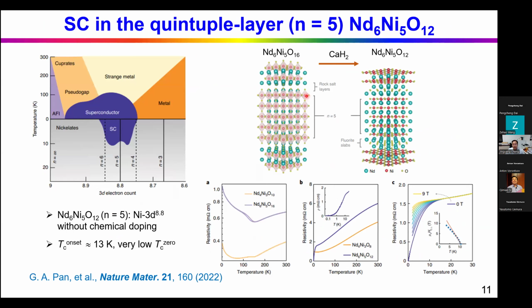Later on, superconductivity was also realized in the quintuple-layer neodymium 6 nickel 5 oxygen 12 thin film samples. But TC is relatively low, especially the TC0, which is below 1 Kelvin. The onset is okay, about 13 Kelvin.